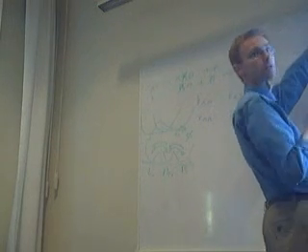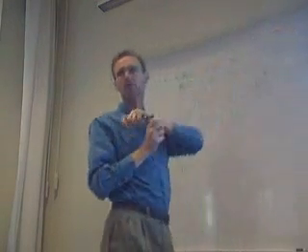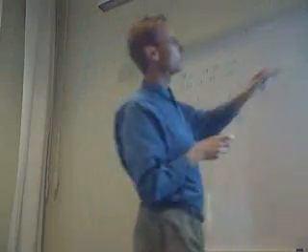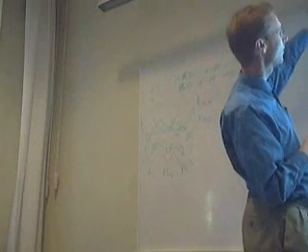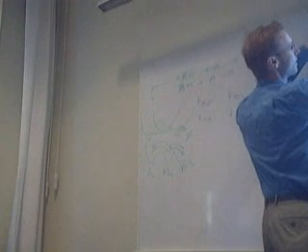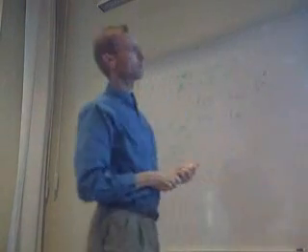So this can grow to the next size up either by colliding with one of these or one of these, and it can fragment, due to grinding, down to one of these, and when it fragments it throws off a dimer of the same chirality as itself. So that's the grinding. So we've got these mechanisms. Beta is the grinding, alpha is the rate at which it adds on an amorphous dimer, and psi is the rate at which it adds on a chiral dimer of the same chirality. And those are the only mechanisms we've now got in our model.